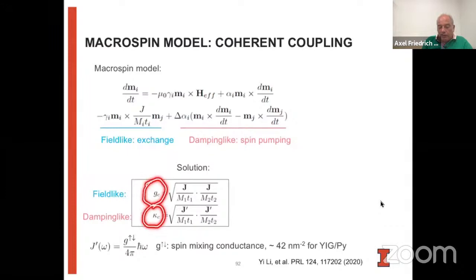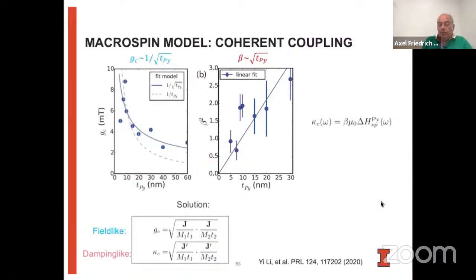Now, what's interesting is this model also tells us that we would expect both the real and the imaginary part of this coupling constant to be inversely proportional to the square root of the thickness of the individual layers. This is something we can easily check. We can use different thicknesses of permalloy. And indeed, when we look at the real part of the coupling constant as a function of the permalloy thickness, we see that it decays as the inverse of the square root, and not simply as one over the thickness, as one might naively expect.